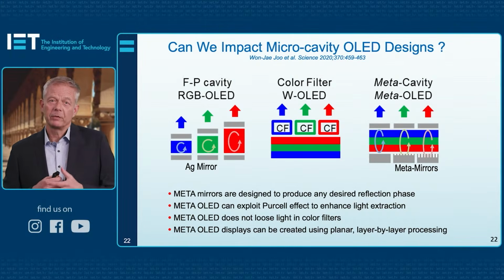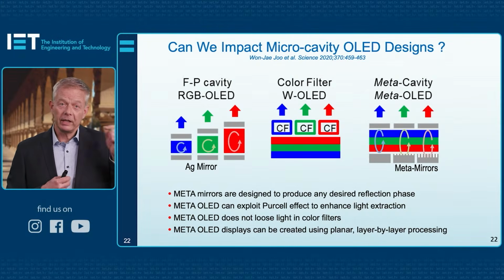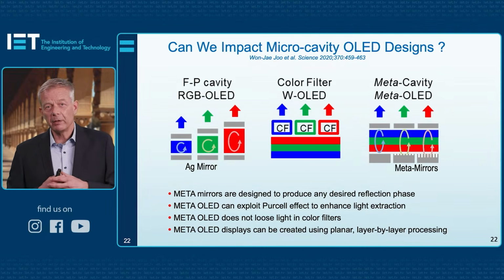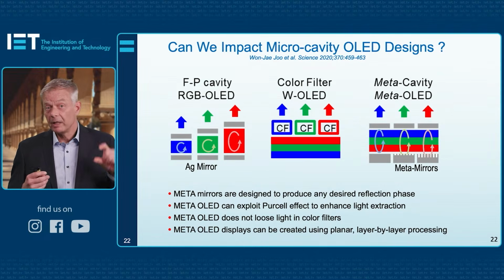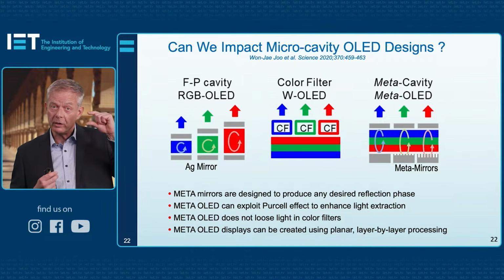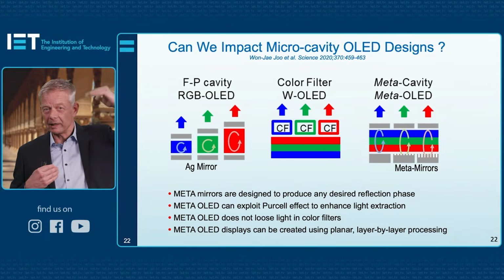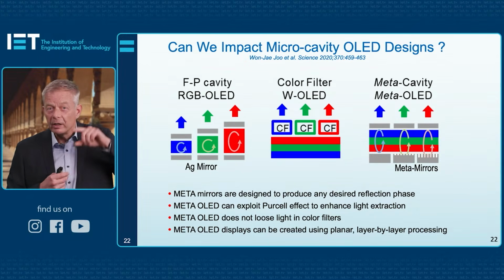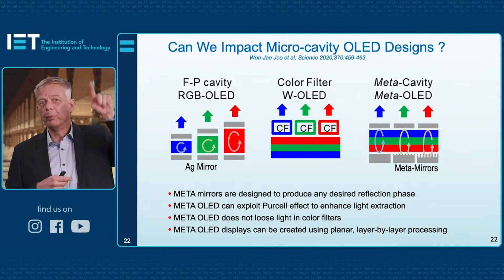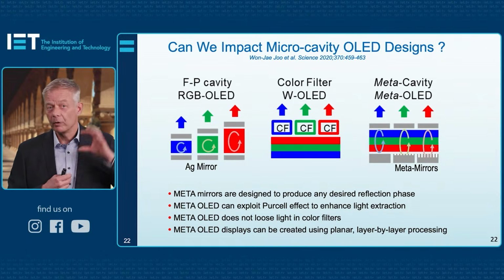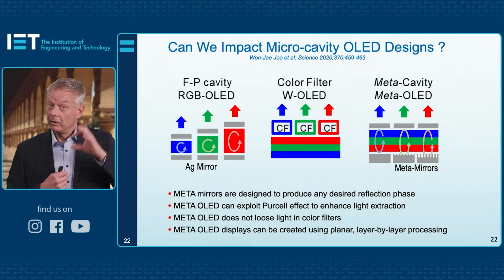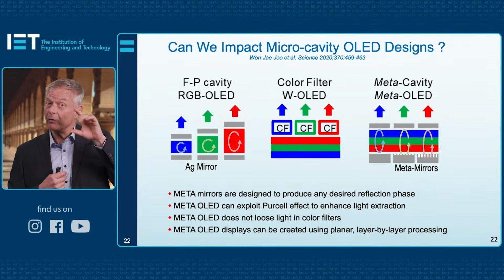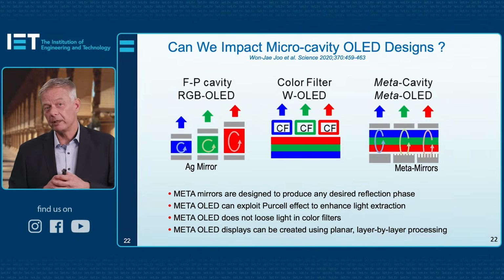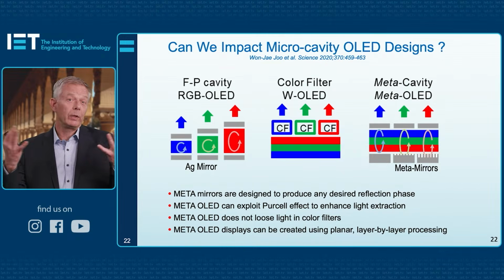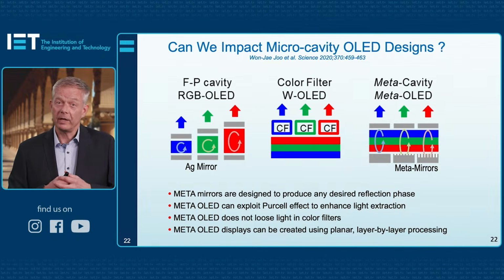Well, on the left side, you see how in the olden days we used red, green, and blue emitters that we clamp between two mirrors, one top mirror quasi-translucent to let light out, but we used the phenomenon of resonance to boost the light emission in the blue for small mirror spacings. For a little bit bigger spacings, we could resonate the larger wavelength of green, and for even bigger spacings, we could start resonating red.